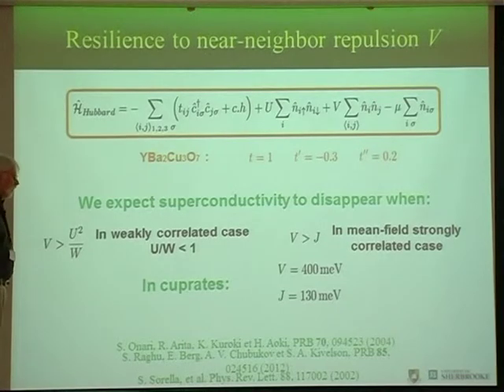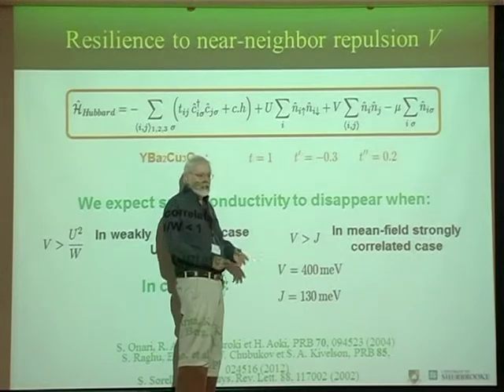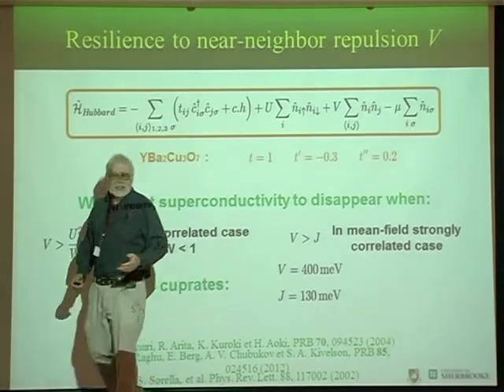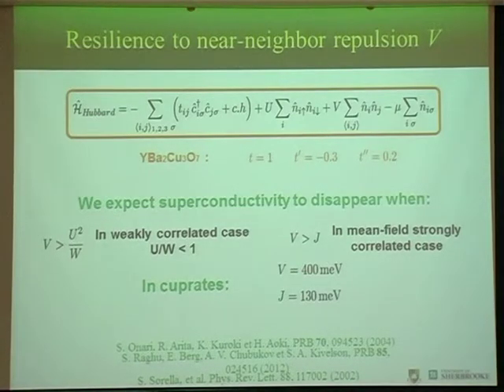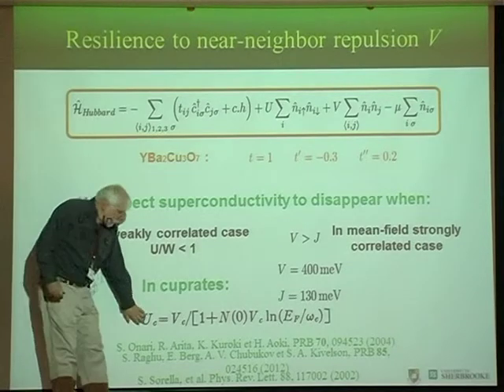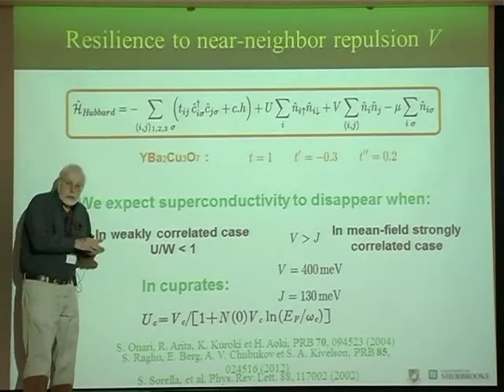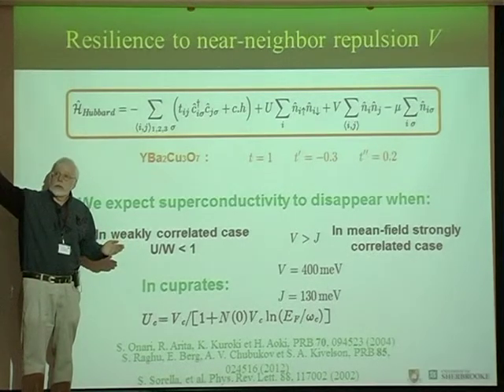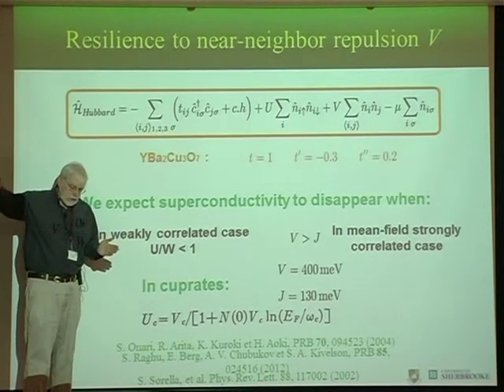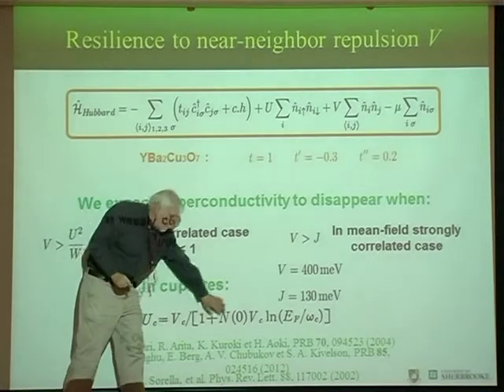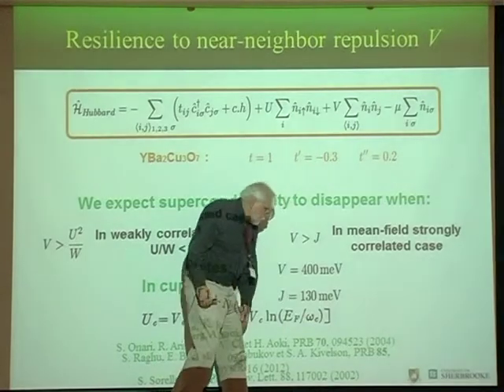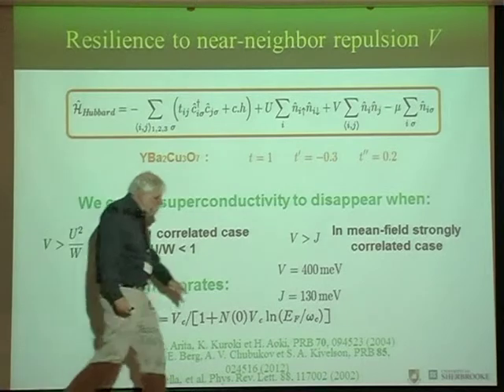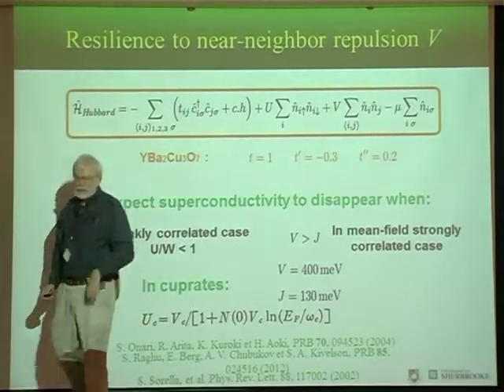Well, okay, the sad part is that if you just estimate V from the Coulomb interaction and the dielectric constant, it is much larger than J in the cuprates. So if somebody tells you J is causing the pairing, you have to ask why isn't V destroying it? Or explain to me why screening is so good in this bad metal. Well, in ordinary Eliashberg theory, the effective Coulomb interaction is screened in the sense that it occurs over a very large frequency scale compared to the pairing. So if you fold this down to the Coulomb interaction in the low frequency range, you will see that it is reduced in this way. But there's a log of E Fermi over the Debye frequency, or the cutoff frequency. And in high temperature superconductors, these scales are not the same, but they're certainly much more comparable than in the ordinary superconductor.